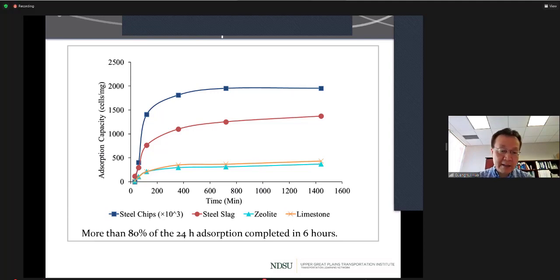And in addition, we found that the adsorption capacity of steel chips is almost more than 1,000 times that of the other materials. So we had to divide the steel chip result by 1,000 in order to put all the data points into one scale. Therefore, steel chips are much more effective compared to other materials. And also we found out that steel slag is a better adsorbent than zeolite and limestone, which are natural minerals. So this is the result we found based on the first set of batch adsorption studies.